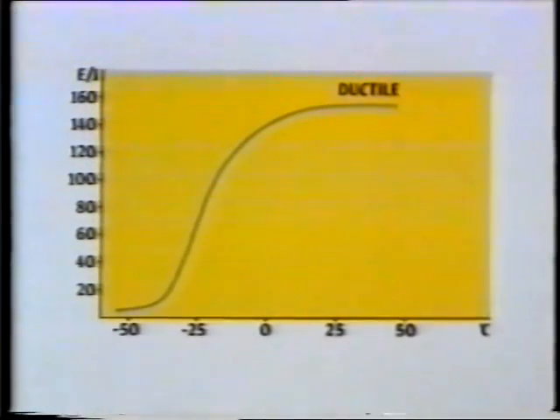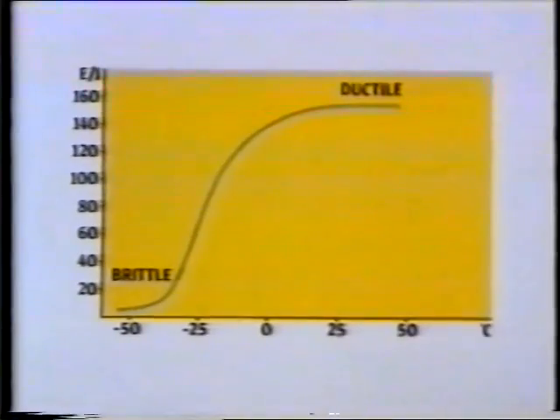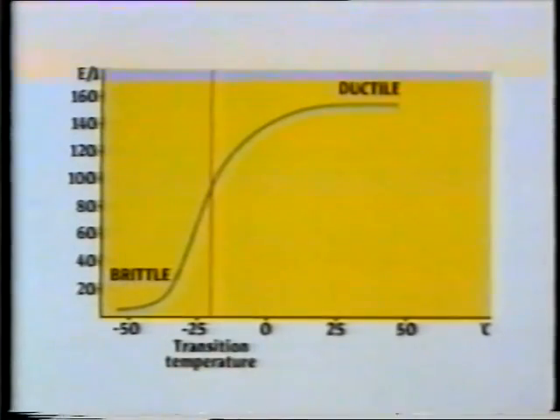On the lower shelf, the steel is no longer ductile and behaves instead in a brittle fashion. Looking at this fracture face, it has a characteristic flatness with small, bright facets. In between the two shelves, the fracture shows both brittle and ductile properties. The transition temperature defines the point at which it's exactly 50-50. There's the brittle region on the left, the ductile on the right.